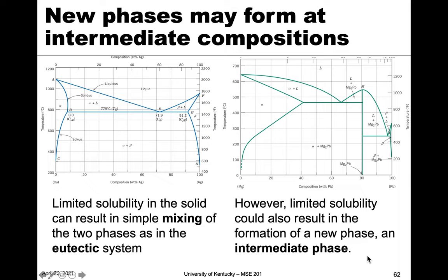We've talked about the eutectic system, and that's the one you see here on the left. It has limited solubility of the two solids, so alpha here — which is the copper component — and beta here — which is the silver component — don't like to mix and form a solid solution, so they form a mixture of alpha and beta. This results from a lack of solubility, and that's where you get the eutectic system.